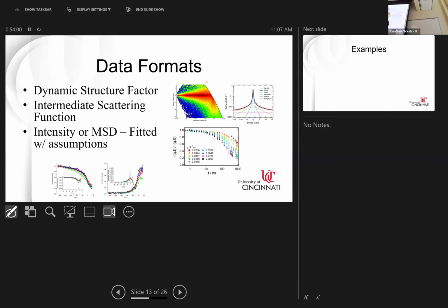This is what spin echo data looks like. This is called the intermediate scattering function. And what you see is it decays from 1 to 0. So your normalized intensity, imagine that this value here reflects your SANS signal. So it's telling you what my structure is. All right, I have a structure as a function of Q. And now I just look at that.